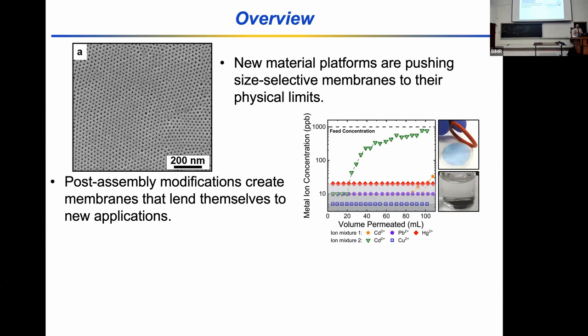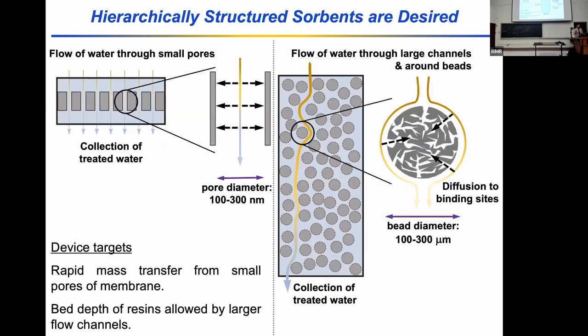And so in the last 10 minutes here, I want to talk a little bit about advancing beyond those thin film membrane adsorbers. So the membrane adsorbers are nice because they have really fast mass transfer. And so we get those sharp breakthroughs and those fast response times. But admittedly, they have pretty limited capacity, right? They're thin membranes. And so there's not a lot of material there to go ahead and capture stuff with.